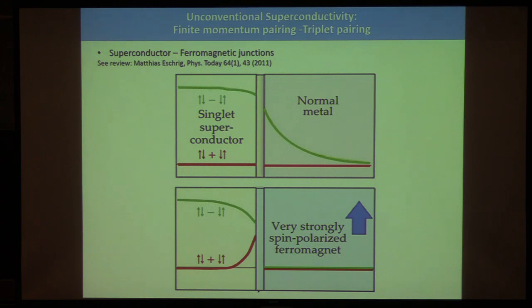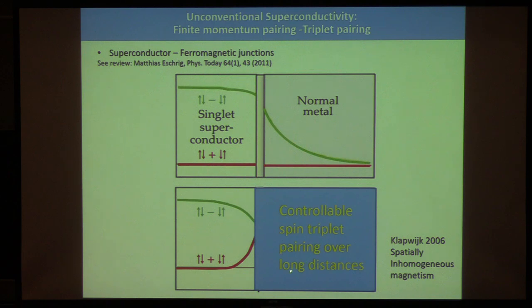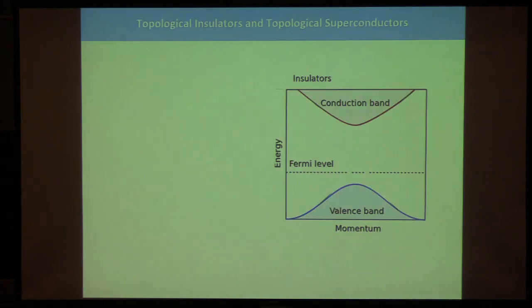And so here the community more or less split. There were further developments in this area that use inhomogeneous ferromagnets. It turns out that if you use a magnet that is not simply polarized in one direction everywhere in space, you can somehow overcome some of these difficulties. But what I'll talk about today is a different kind of strategy which replaces this material here with a material that has no magnetism altogether, has only spin-orbit interaction, and yet will generate the FFLO state in a very, very robust manner, in a way that in fact will not depend on the strength of time reversal symmetry breaking that exists in this material. And you'll see this in just a bit.